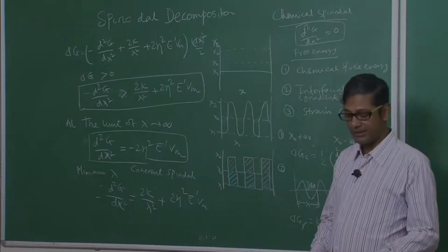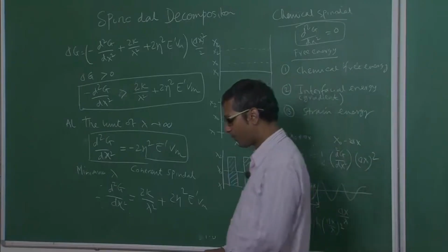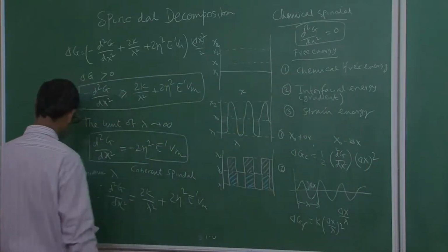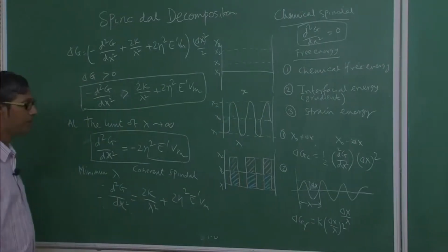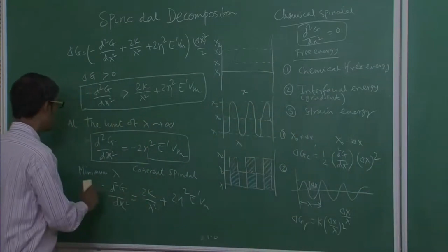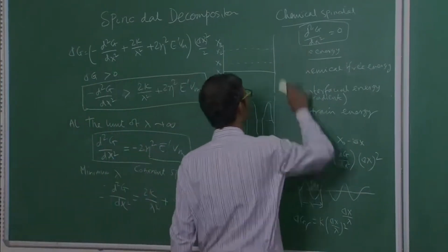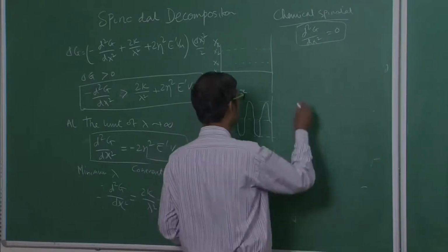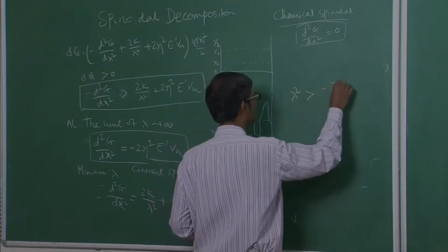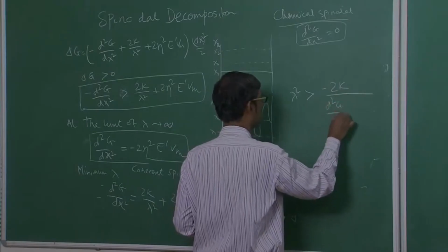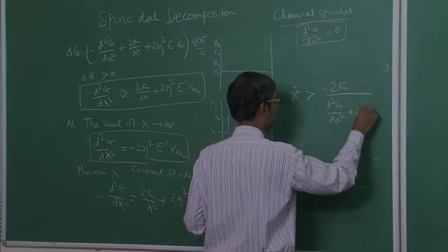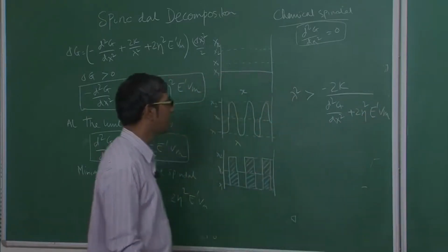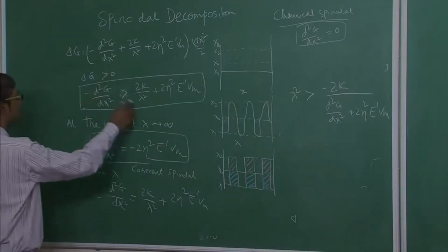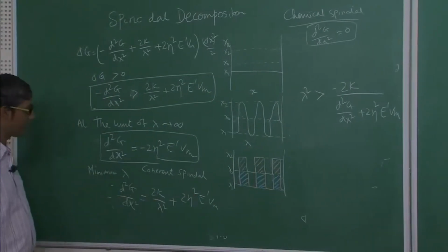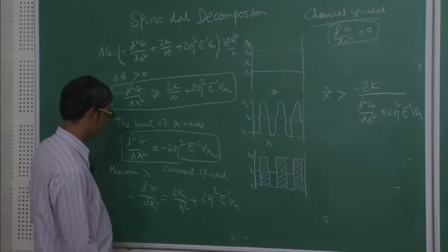Okay, so now the last thing which is important is that the wavelength of compositional fluctuations or modulation developing inside a coherent spinodal must satisfy the condition like this. Okay, the wavelength of compositional fluctuations developing within the chemical spinodal must satisfy this condition. How do you obtain that? Very simple. You make this, basically coming from this equation, that is what it is. So if I simply take this equation, let me write it.